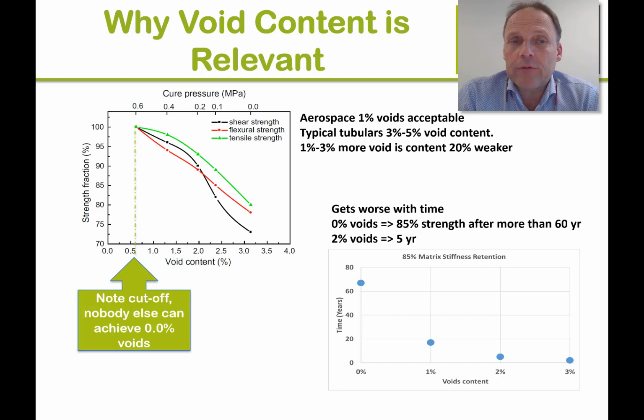Please note in that graph, what I put in the yellow arrow box, is that this graph has a cutoff at 0.6% void content, because normally manufacturers cannot go below 0.6% of void content. Now the graph on the left hand side is one that is instantaneous, it's about at any given time how you should compensate for voids in the material strength. The chart on the right hand side accounts for the factor of time, and what you see there is that when there's 3% voids, 85% of the remaining strength is reached after 1 to 2 years, and after that the material will be even weaker.